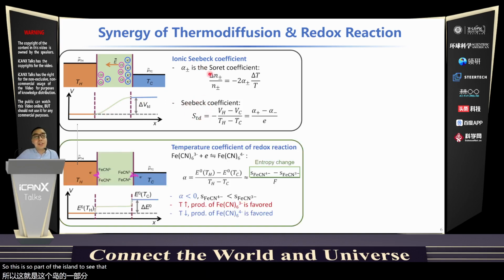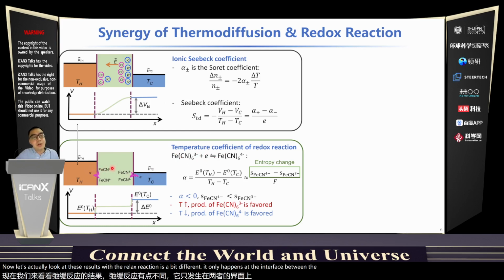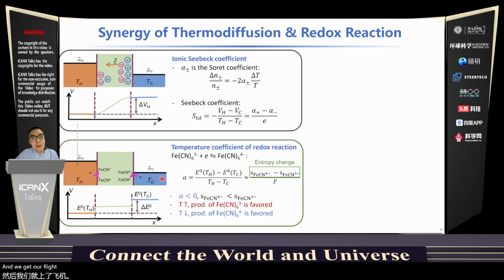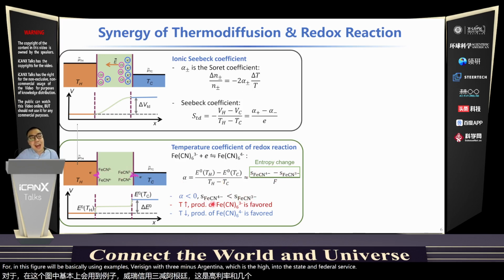Now let's look at the redox reaction. The redox reaction is a bit different. It only happens at the interface between the electrode and the electrolyte. And it turns out that the thermal voltage is actually determined by the entropy change of the redox reaction. In this figure, we use the example of ferricyanide with 3- charge, which is the high entropy state, and ferrocyanide ion with 4- charge, which is the lower entropy state.